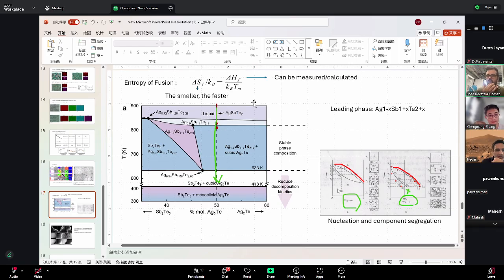Yeah, exactly. So you don't need to collect from 10 to 90. You need to collect from 20 to 23. It's 3 degrees. Yeah, exactly. You don't need the whole pattern. You just need to collect a few points of temperature, and you just measure with XRD. So I think it could be that, right?